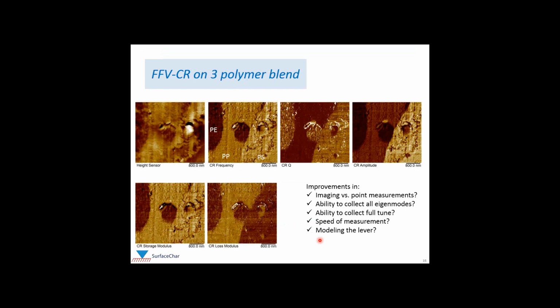Bede is going to be discussing this in detail in his part of the webinar, but just to give you a little bit of a taste of contact resonance with all these improvements that I just discussed, what the data might look like. And here's some data that we collected with Bruker's fast force volume contact resonance on our three-polymer blend. This is our contact resonance frequency and quality factor. We also map the amplitude channel. And then we have our calculations of our storage modulus and loss modulus channel.